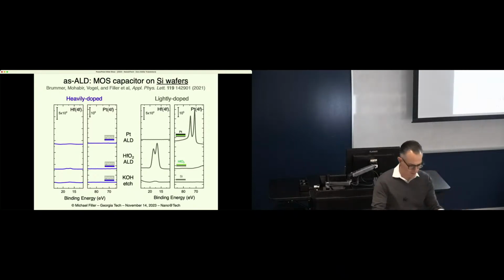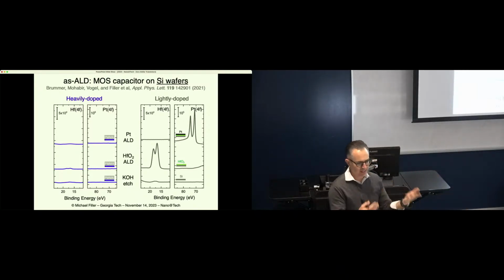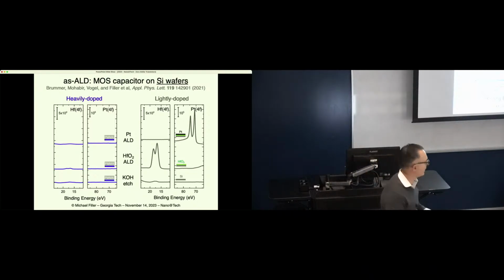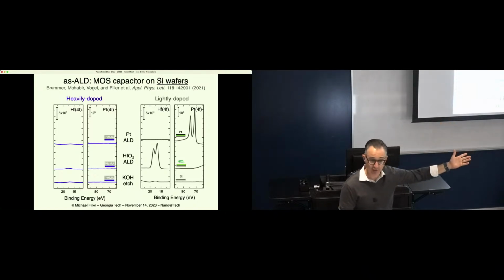Okay, so now we have a mask on the surface, and the next step will be to see whether we can selectively deposit the gate stack. Again, trying to eliminate anything that's not a chemical process. So here on the bottom is what you're seeing in the hafnia and platinum regions of the XPS, so nothing because I haven't put anything down yet.